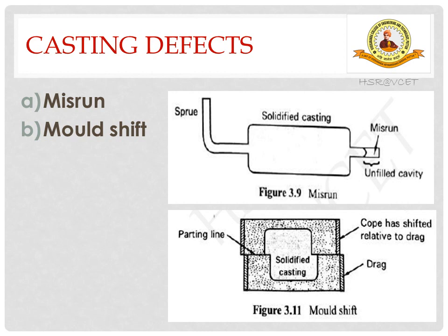Some of the remedies by which this can be avoided are: the sand should be properly rammed. Molding sand or core sand should not be too coarse to promote metal penetration. The proper control of metal temperature, that is nothing but the fluidity of the molten metal, should be maintained suitably so that the molten metal can flow to every corner of the cavity.